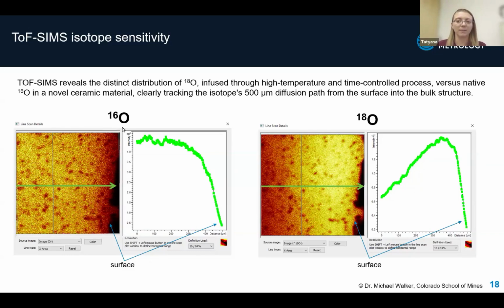Unlike other techniques that only measure total oxygen content, ToF-SIMS can actually distinguish between isotopes. The line scan helps us quantify the colors in the image, showing how oxygen 18 penetrates as a function of distance from the surface. This ability to both image and quantify the distribution of oxygen 16 and 18 simultaneously makes ToF-SIMS an essential tool for studying diffusion mechanisms.